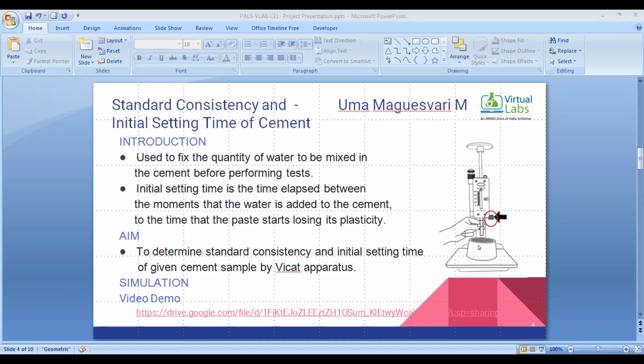Initially it will go to 0. After some time it will reach a reading of around 5 to 7. For each 5 minutes we have to note down the reading, until the reading shows 5 to 7 mm. The time duration between the water being added to the cement and the time when the reading is between 5 to 7 is the initial setting time.